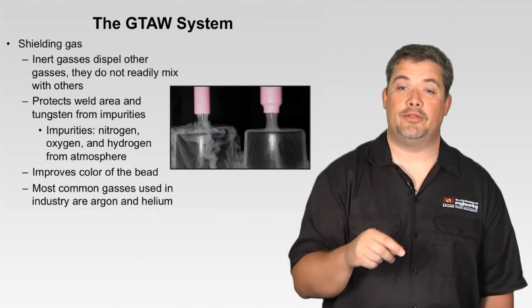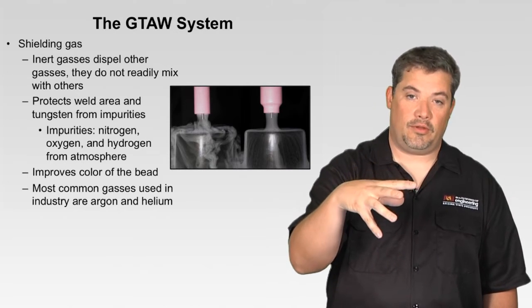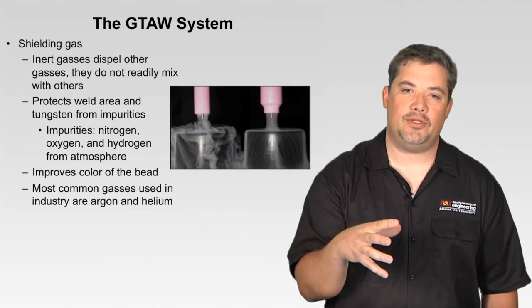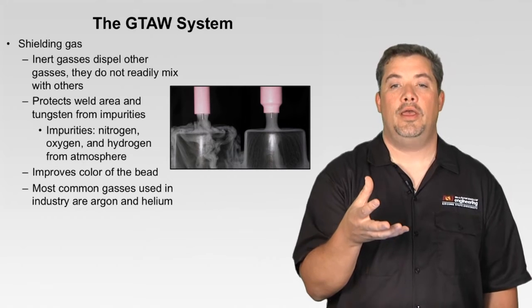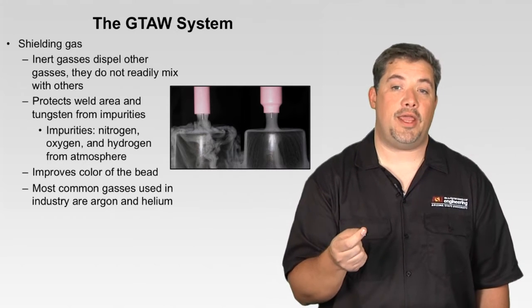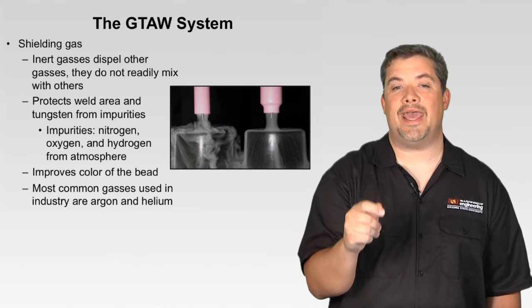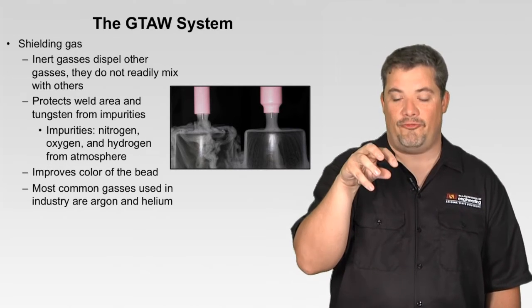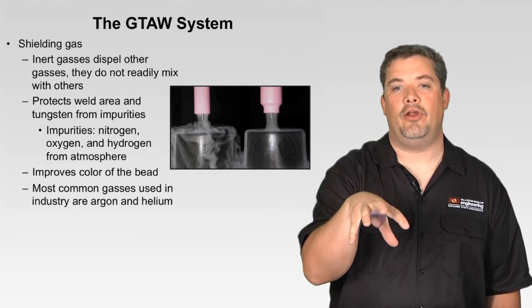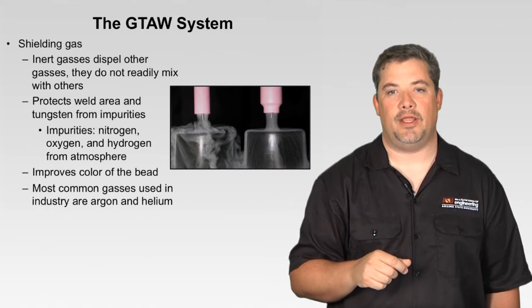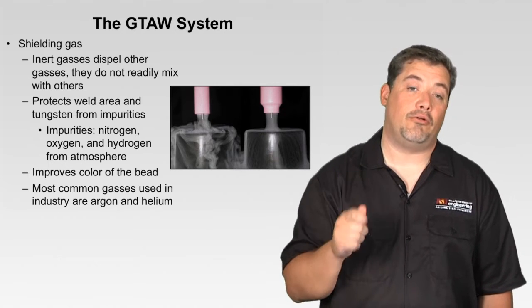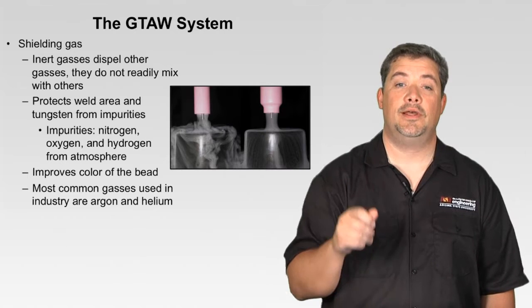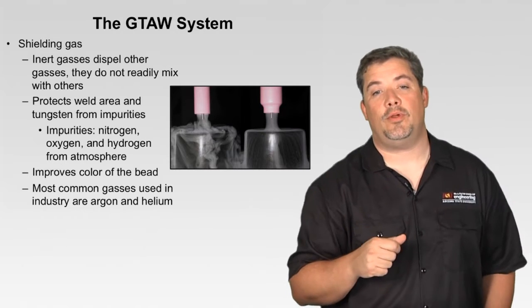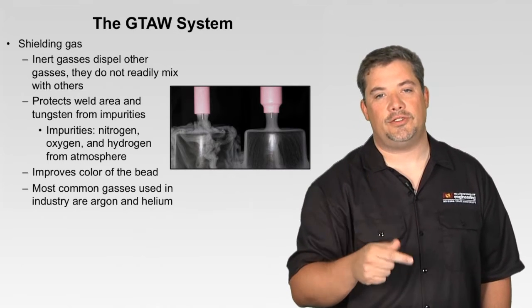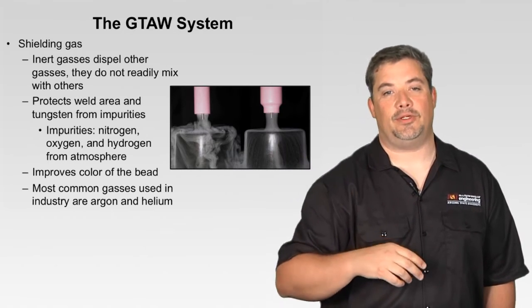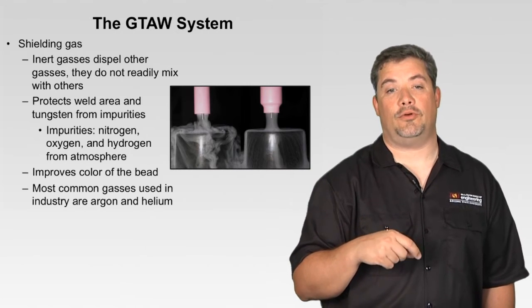But you can see how we're literally using smoke and mirrors in this image, where the gas coverage is there, doing an adequate job, but you can see there's a lot of potential spots for inadequate gas coverage. If you look at the image on the right, where it comes out at a nice laminar flow, that's using a gas lens, and that gas lens filters that shielding gas to give very good coverage, and you can see it in that image, night and day between the two. So gas lenses are a great tool to use in TIG welding to help your shielding gas protect that weld area. It also protects that tungsten from impurities, and some of those impurities are nitrogen, oxygen, hydrogen, any of the other gases, especially the reactive gases that could destroy our part.